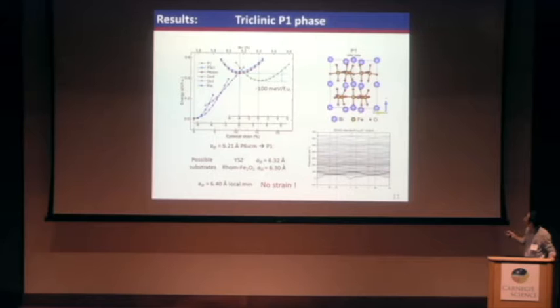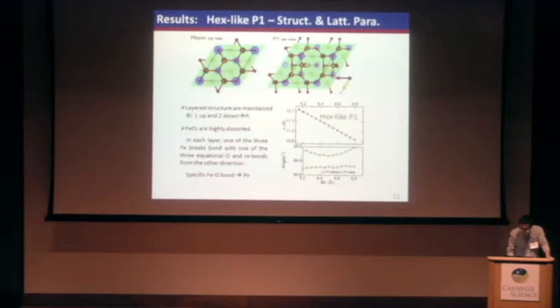It's pretty much looks the same with the hexagonal phase, and it is dynamically stable. Then we compare the structure between the P63cm and the P1 phase. We already noticed that the layered structure has been maintained. That means for the bismuth layer, the 1 up, 2 down, or 1 down, 2 up, it is maintained, and it contributes to the polarization, out-of-plane polarization.